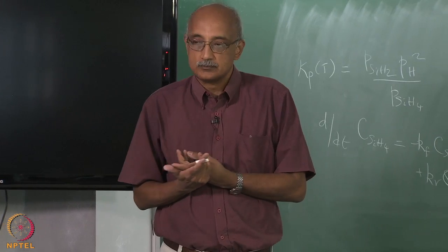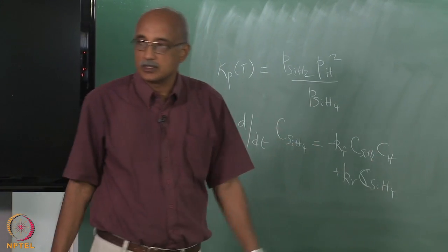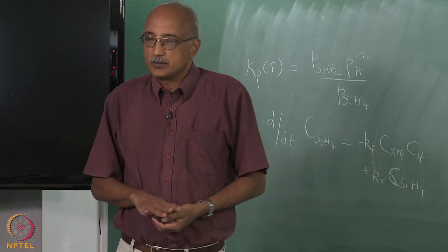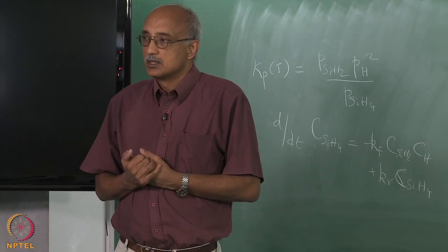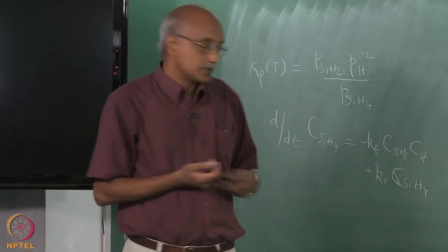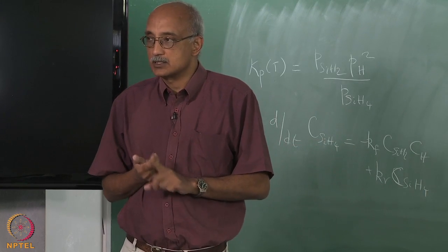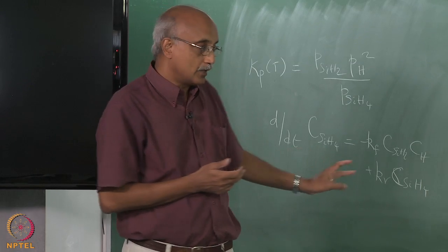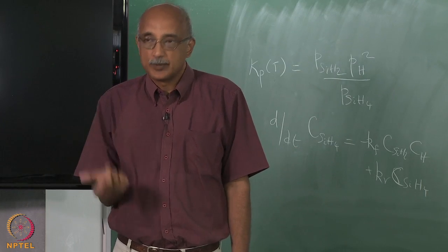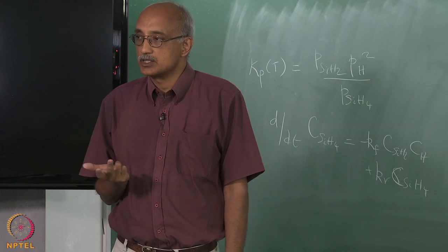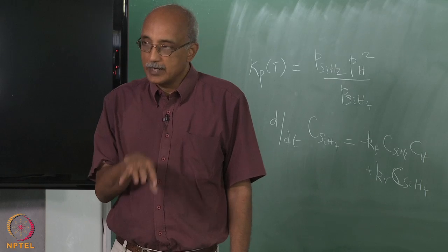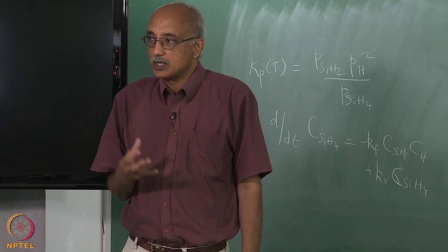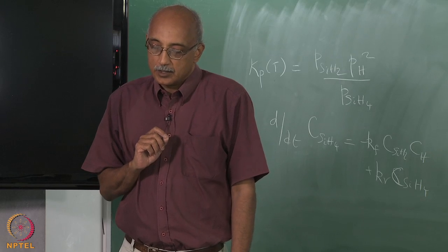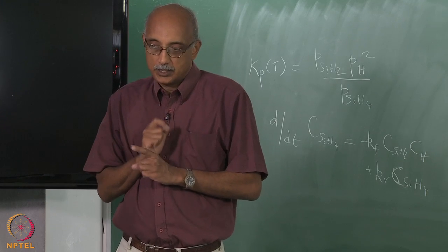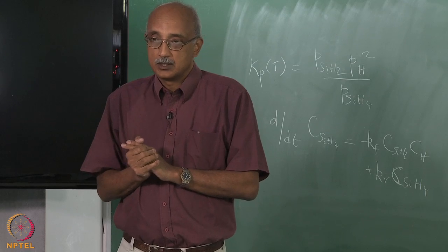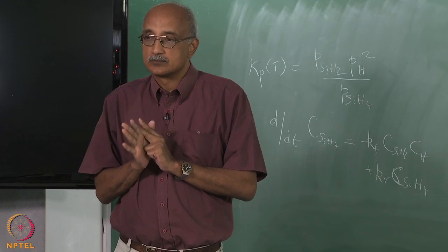So, there could be literally dozens or even hundreds of these chemical reactions constantly going on. Even in the equilibrium case, even if you can assume that equilibrium exists, how do you handle all that? There are going to be simultaneously 100 reactions going on, with rate constants involved. And it gets even more complex in the kinetically limited case, because you have to solve these equations simultaneously with your momentum conservation and energy conservation equations, so that you know the local prevailing velocity, the local temperature and so on, in order to do these calculations. And so, dealing with the gas phase reaction part of it, even in the case where you can assume chemical equilibrium, is challenging.